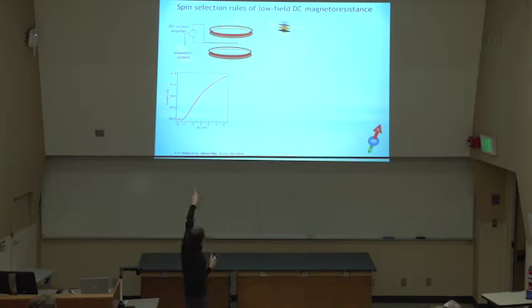This, by the way, is room temperature data. So obviously at 0 millitesla, you have no magnetic polarization. Now you turn on your magnetic field to, I don't know, 5, 6 millitesla. Guess what? You still don't have magnetic polarization. You don't change anything about the polarization. For all practical purposes, polarization is 0. Yes, it's not 0, but 10 to the minus something. How can you have percentage range changes?